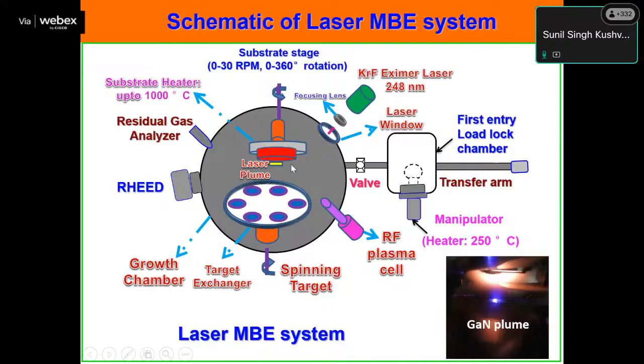After transferring, because it's a quick process, maybe within 2 minutes, you take out the transfer arm, then close the gate valve. Then within 10-20 minutes, your pressure will be as good as 2 times 10 to the minus 10 millibar. We have to maintain the pressure of the main growth chamber always in the UHV region. So in any MBE or laser MBE system, we have these two chambers.